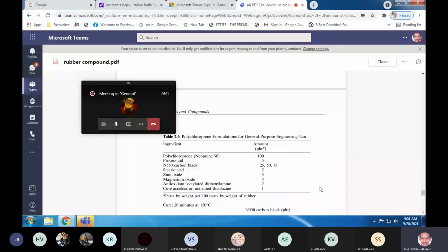And that also helps in maintaining process safety. Magnesium oxide, process safety. Zinc oxide is a cross-linker. So we use the zinc oxide at the end in chloroprene rubber compounding. In all other rubbers we discussed so far, including NBR, we add the zinc oxide in the beginning. That is the order of addition. Whereas in chloroprene rubber, we are strongly advised to use zinc oxide at the end, because that is a cross-linking agent.